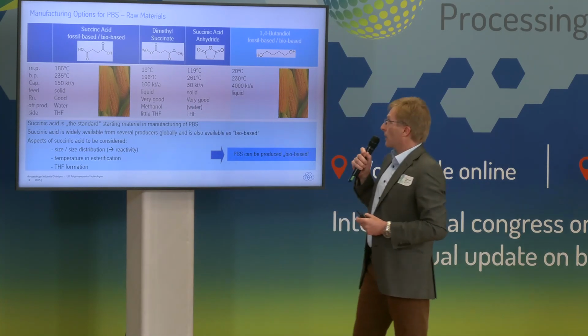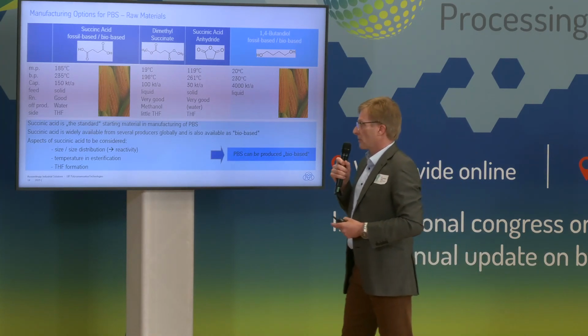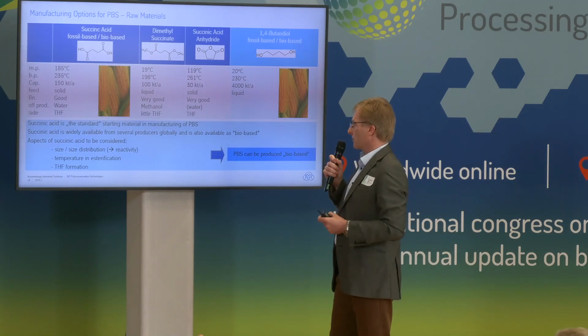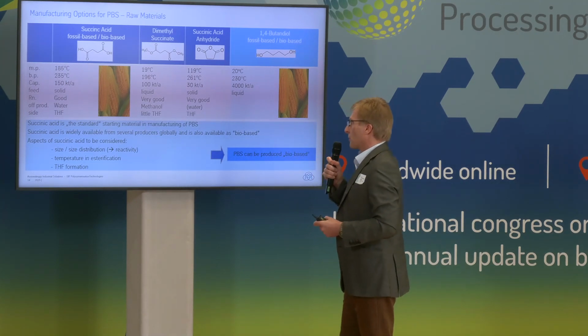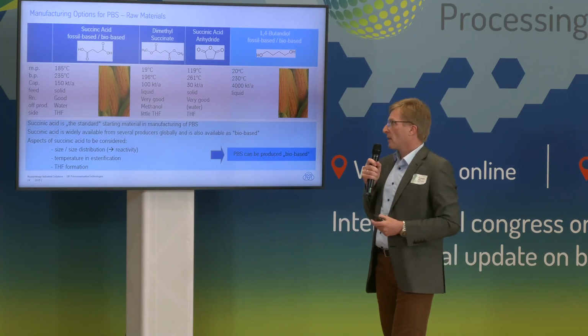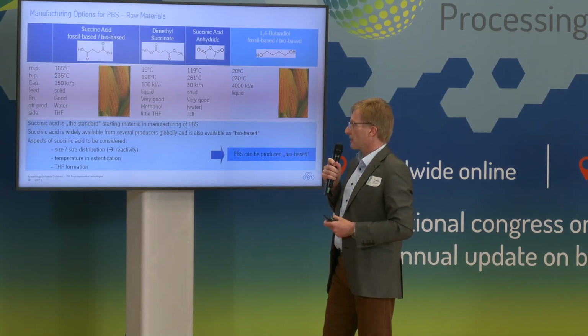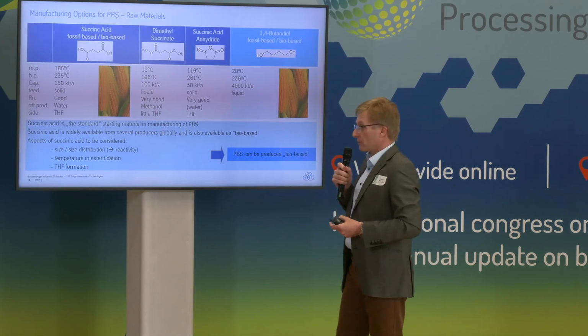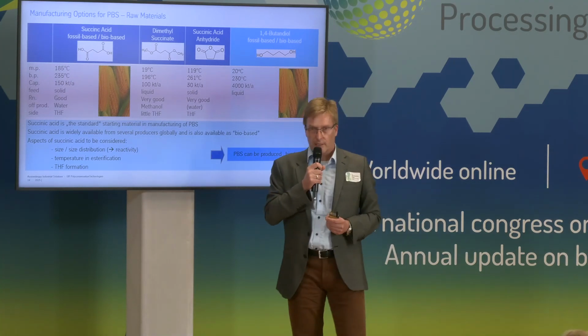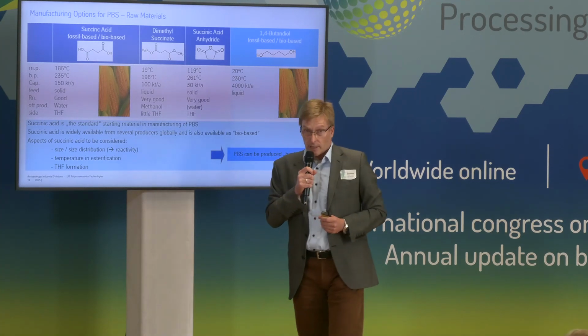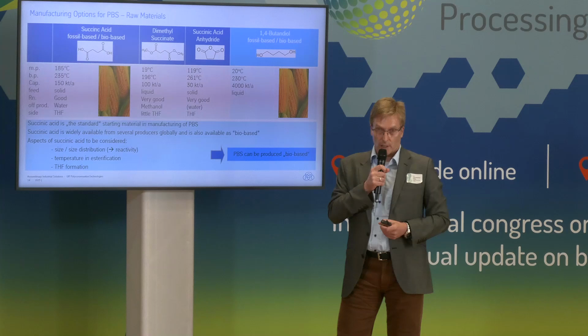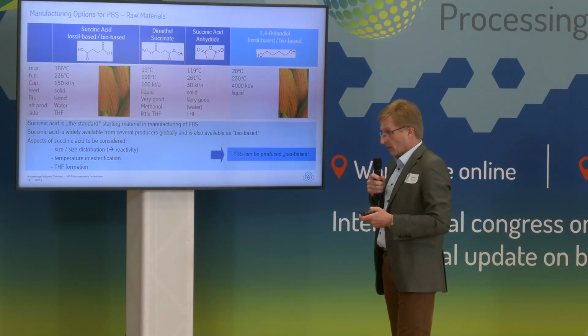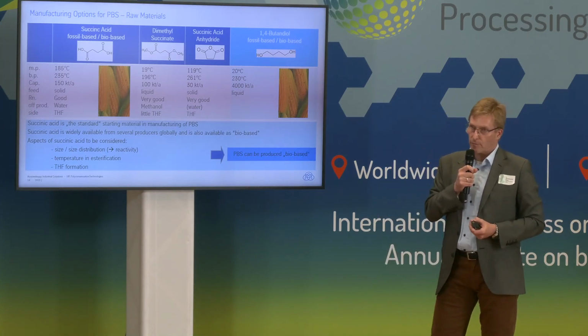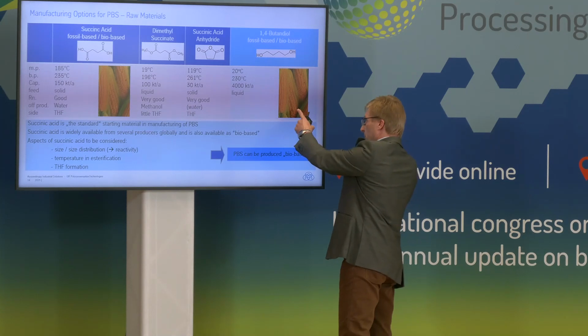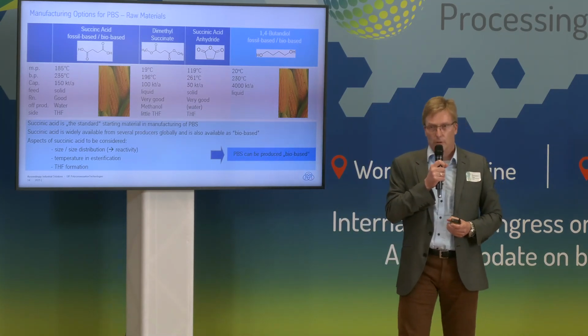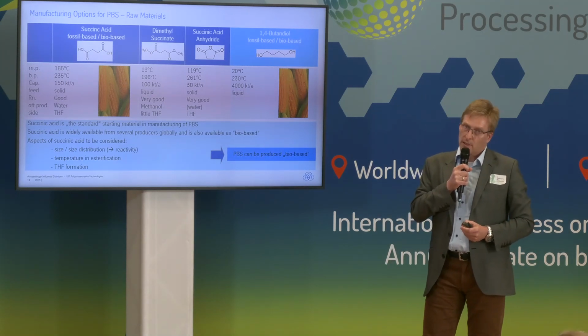To sum it up, why not look at DMS as a good alternative for manufacturing of PBS compared to succinic acid, which so far is still the standard in manufacturing of PBS. Of course, succinic acid is widely available from several producers globally, and it's also available as bio-based. But there are some aspects you should consider if you use succinic acid. It comes typically in different size and size distribution values depending on the manufacturer, which makes the esterification process a little bit more tricky. And you also have a higher temperature in the esterification, which in the end generates much more THF side product compared to starting out from DMS. To sum it up, there are different choices for manufacturing of PBS from different raw materials. The good news is you can also have butanediol as well as succinic acid coming from completely bio-based sources, so you can make 100% bio-based PBS if it's desired.